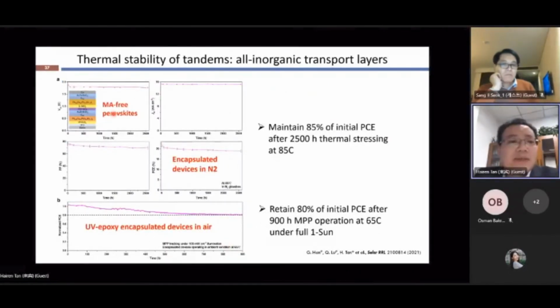And at the end, we fabricated the tandem devices using only metal oxide as the charge transport layer, and we also use MA-free perovskite for both subcells. We found that the tandem devices can have very promising thermal stability. They can maintain 85% of their initial performance after thermal stressing for 2,500 hours. I think this will pass the IEC standards on this point. We also found that even under MPP operation, it can still maintain about 80% of its initial performance after 900 hours of operation at 65 degrees.